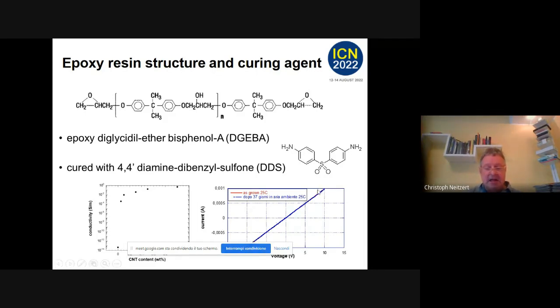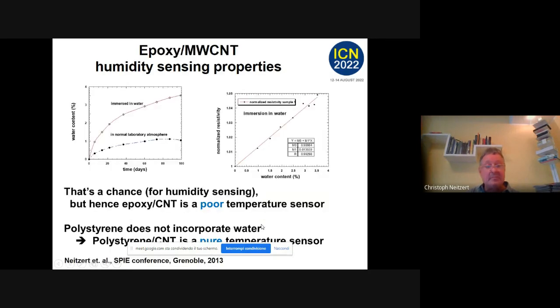You see these after growth, and then after 37 days in ambient, for example, no change can be seen. It's a very stable system. But epoxy takes on water. So what happens? We immersed it in water.